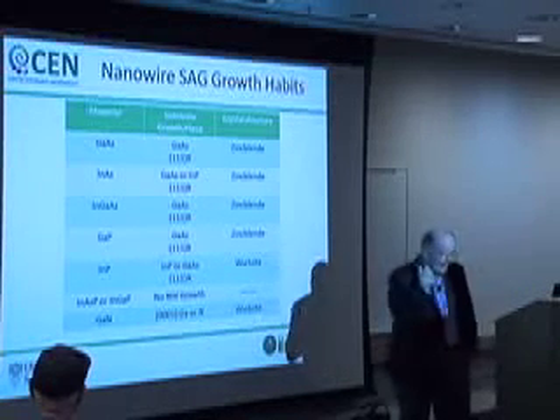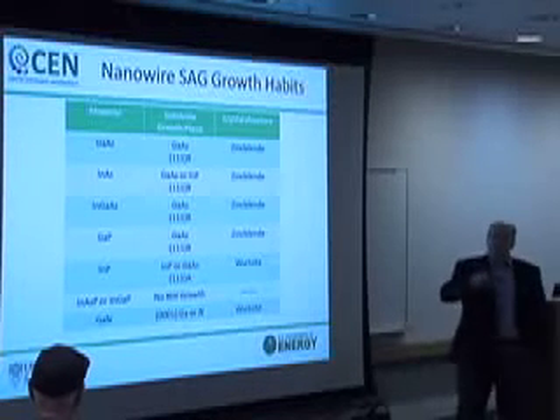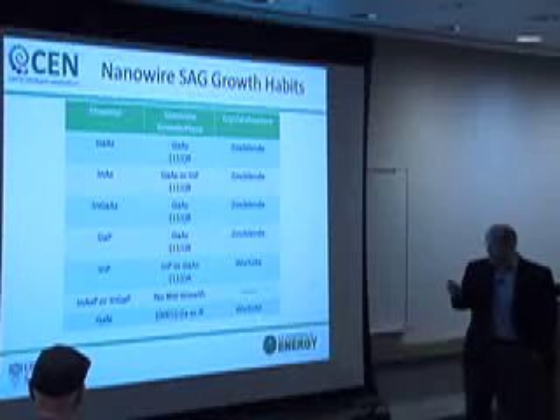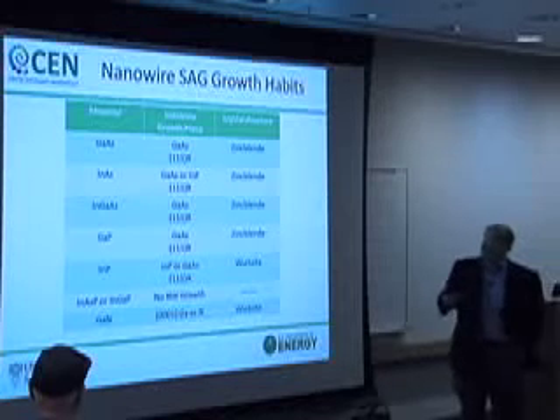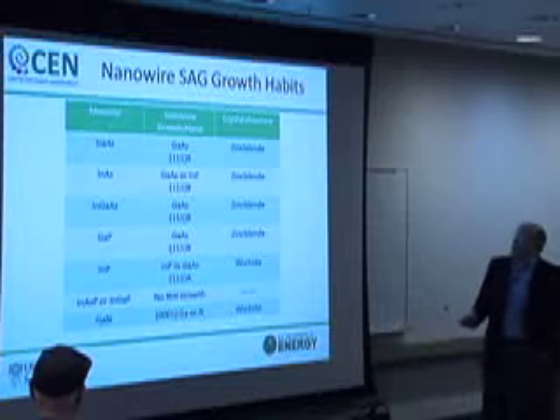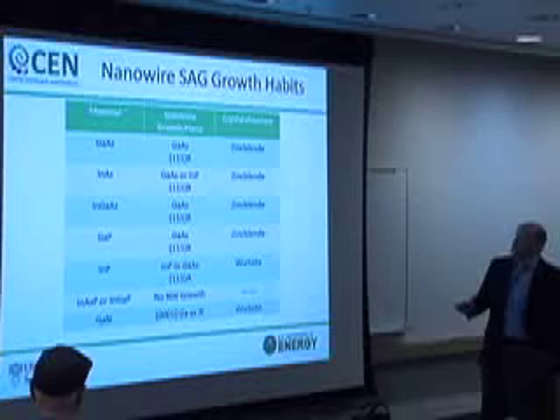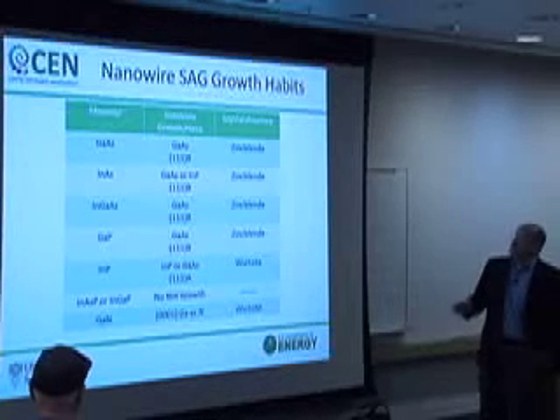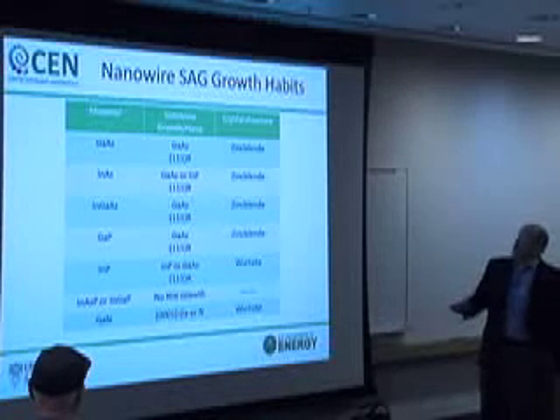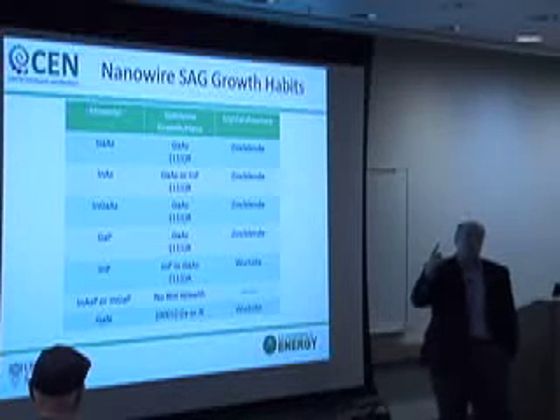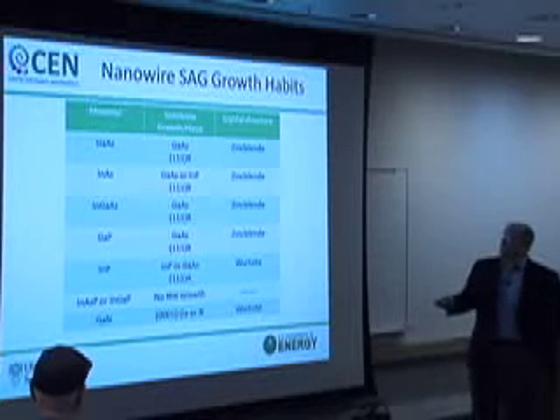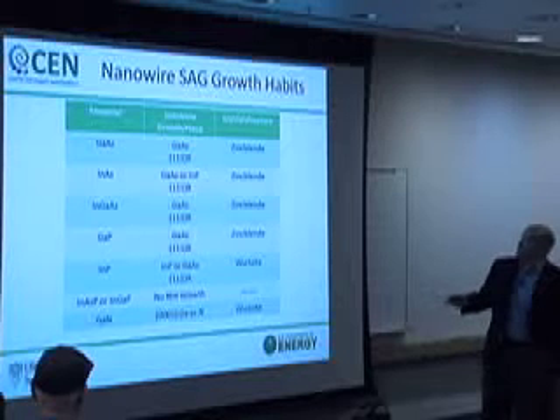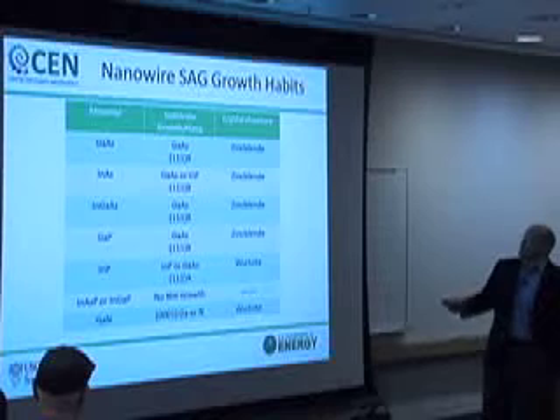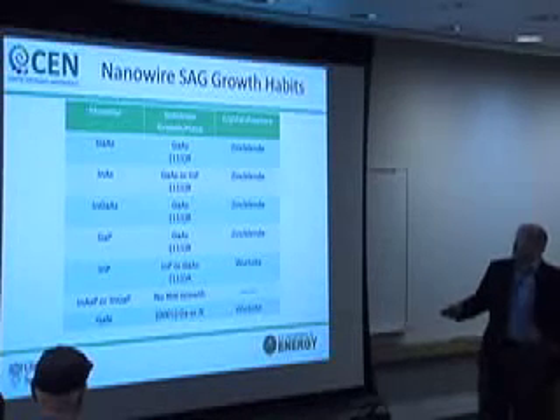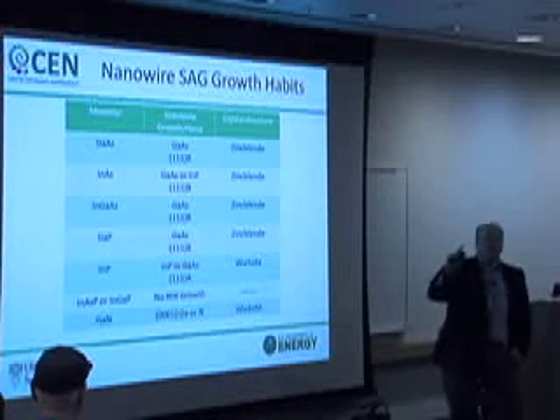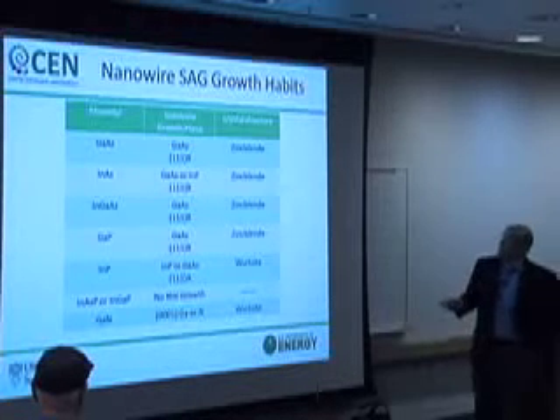All right, so I have a whole story about what happens when you grow different materials on various substrates in this way, and I tried to summarize it with one view graph. At the risk of cutting out too much discussion, let me just say that in order to grow these as nanorods, using MOCVD as a growth method, so that the nanorods are vertical and well controlled laterally, you have to grow so that these structures are growing along the 111B orientation. Okay? So a lot of the work that we've done is we've chosen substrates that are 111B, and we can grow arrays of nanorods to almost arbitrary, well, let me not exaggerate, we can grow them pretty tall and still maintain very narrow lateral dimensions.